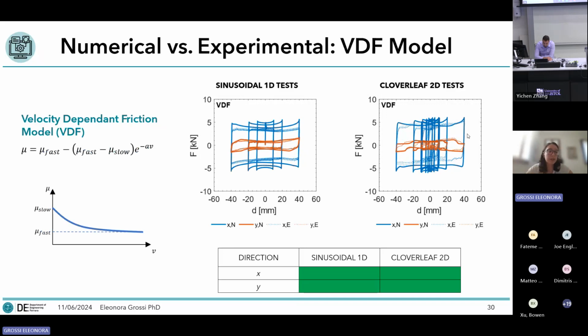So I tried a different constitutive law for the friction, and I investigated a velocity-dependent friction model. This model is a function of a friction coefficient at a low velocity, a high velocity, of a parameter A, which simply defines the curvature of this curve, and of the sliding velocity. You can see that the comparison between the experimental and numerical test is slightly better than before, especially for the cloverleaf test. And this was quite good for me because I can use this tool to develop a virtual lab tool. And this is quite efficient because I can improve the design of my device.